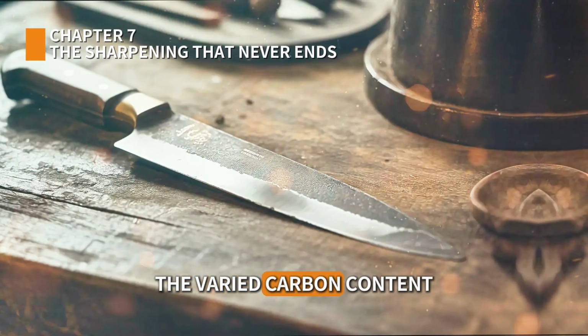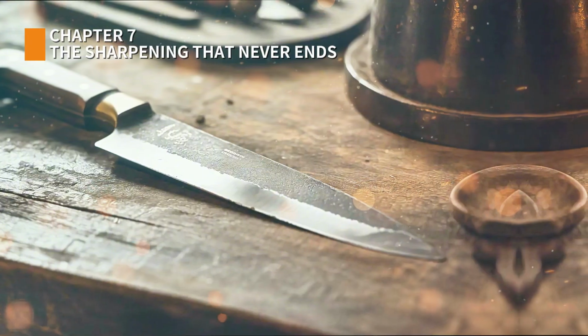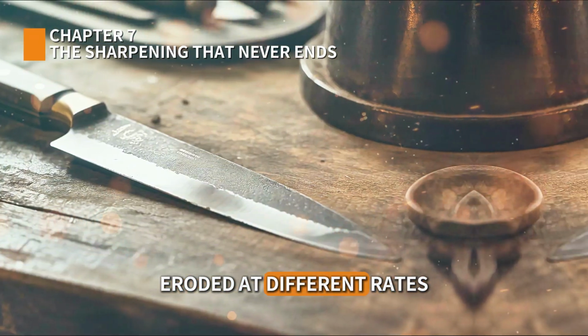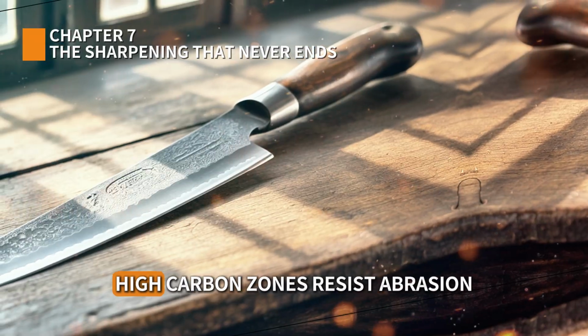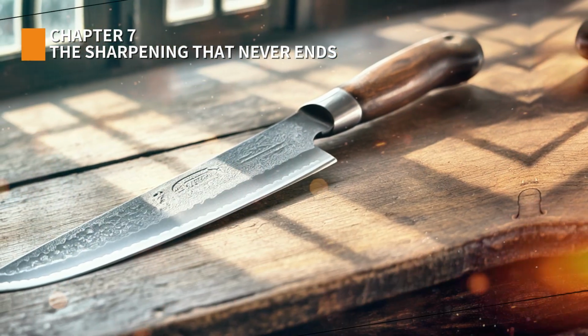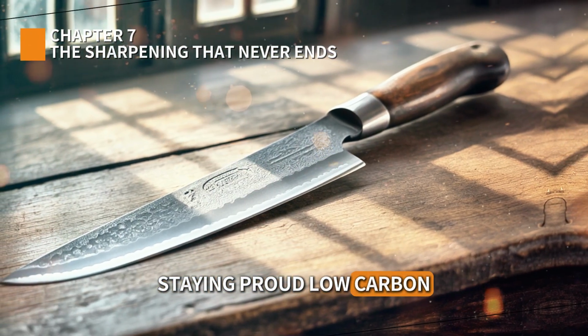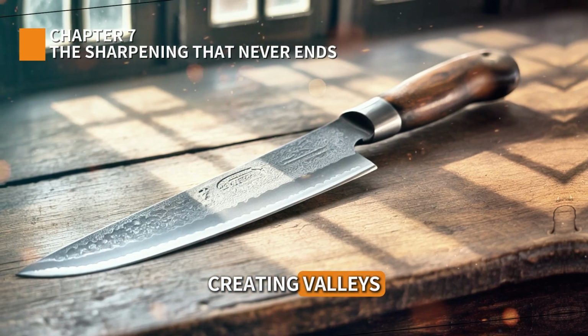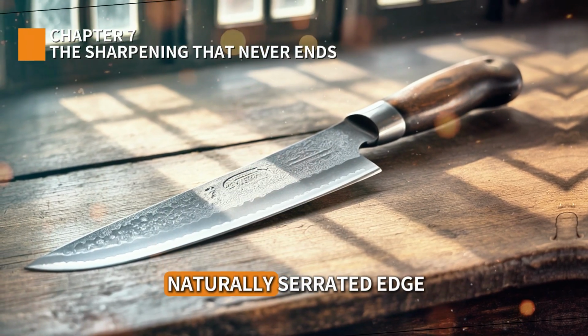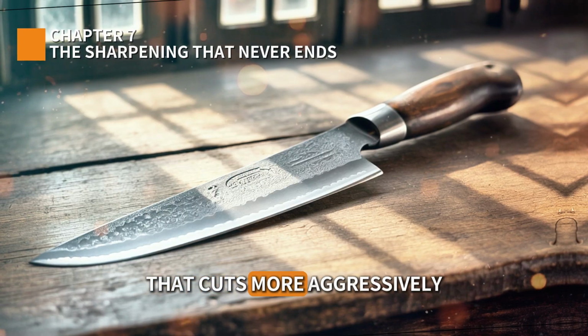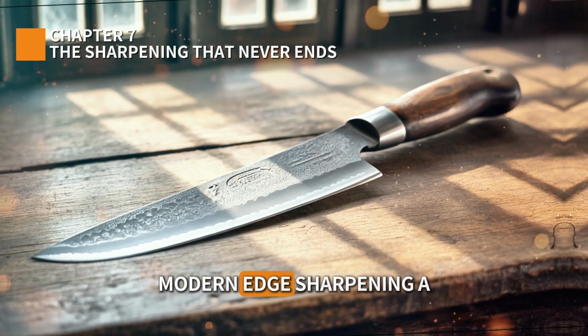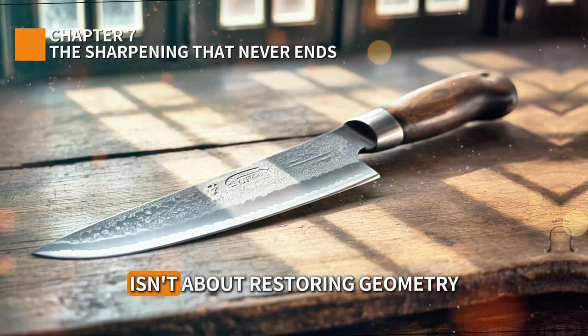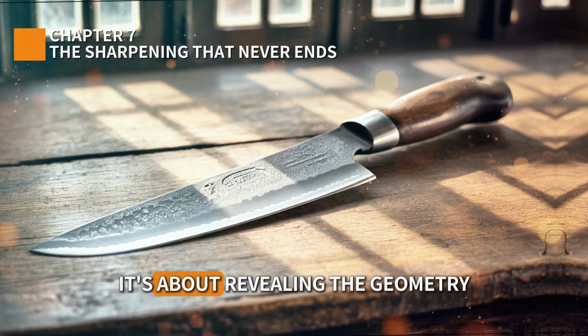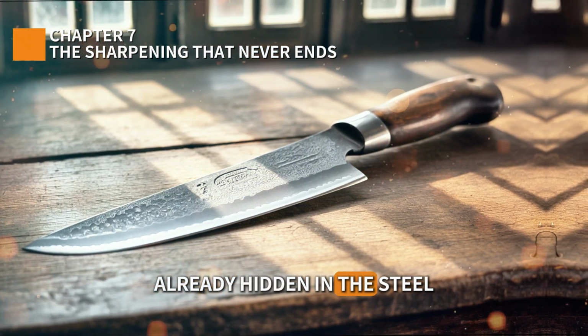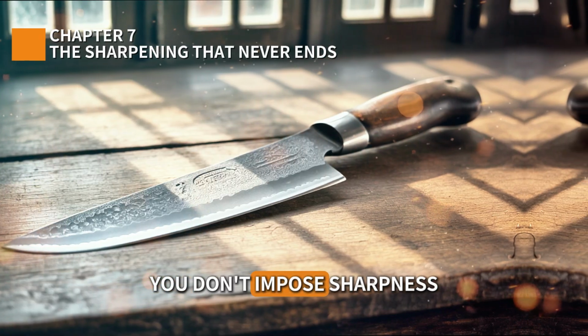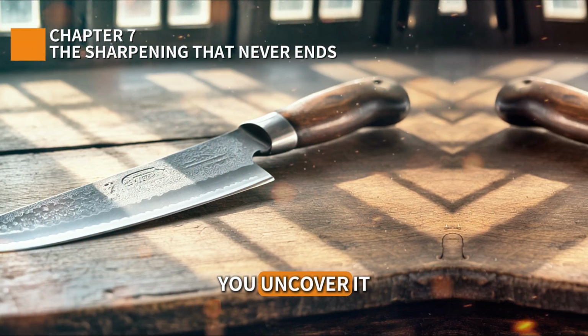The varied carbon content in pattern-welded steel means different areas erode at different rates during sharpening. High carbon zones resist abrasion, staying proud. Low carbon zones wear faster, creating valleys. The result is a naturally serrated edge that cuts more aggressively than a polished modern edge. Sharpening a medieval blade isn't about restoring geometry, it's about revealing the geometry already hidden in the steel. You don't impose sharpness, you uncover it.